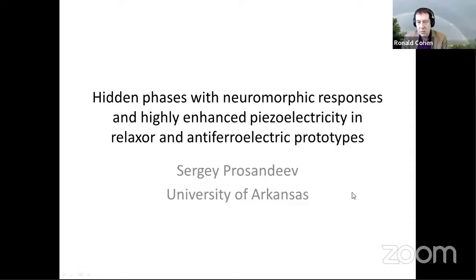This is a matter of treatment of the results, which allows us to calculate the strengths of these clusters. Because it is a very wavy way in which the dipoles can contribute to this cluster. When we take one dipole, the nearest dipoles can look in different directions, but one of them can be in the same direction. So this connected cluster spreads in this last direction, etc., etc.